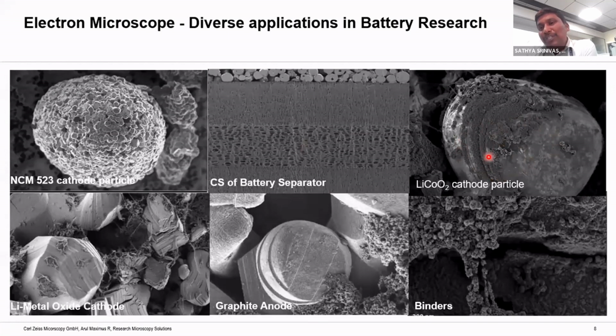And one more example of the cathode particle: understanding the shape and size is one part, and understanding the deposition on the particles is another, what exactly happens after particular cycles, how these cathode particles are deposited with maybe the ionomers, maybe the binders, or some other materials, when the electrodes are in working condition, or after a few cycles. So this is not just clear high resolution imaging. You can understand the surface information, measure the porosity, measure the size of those pores, understand the deposition on a particle, and how the efficiency relates to the deposition and surface information of those particles.